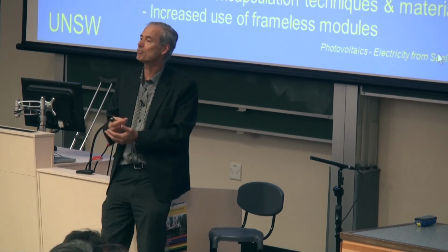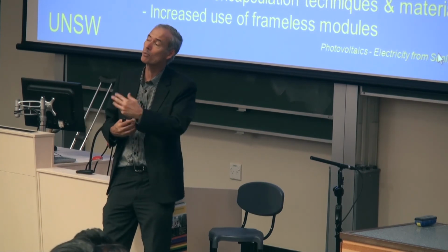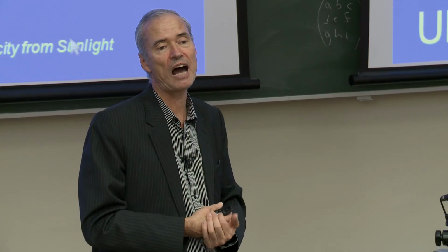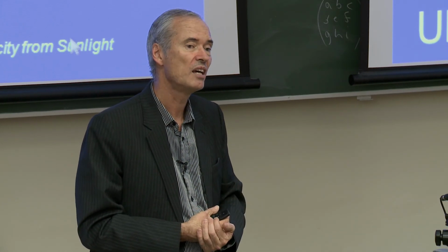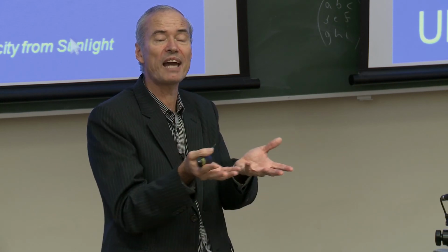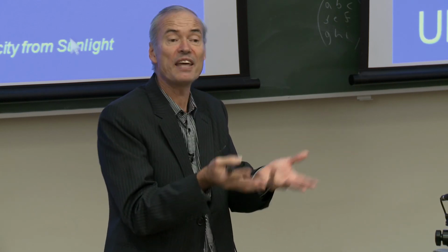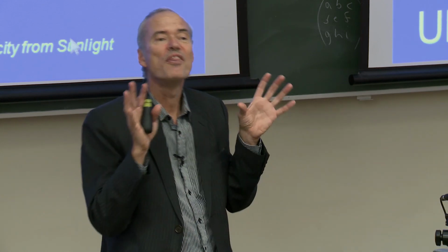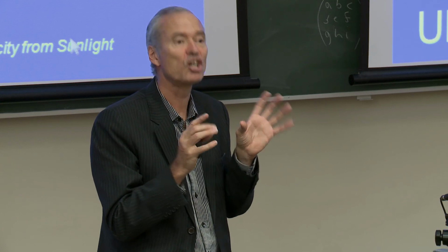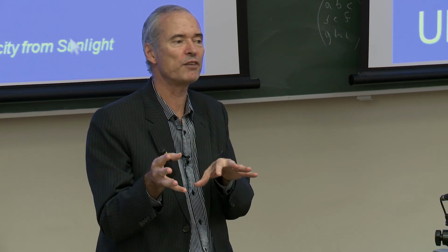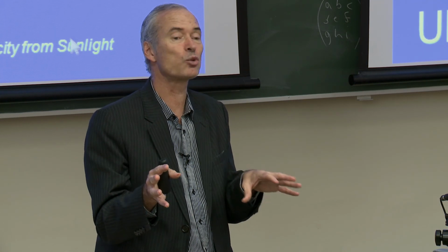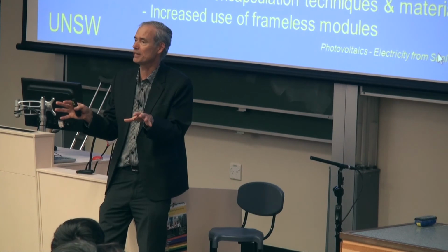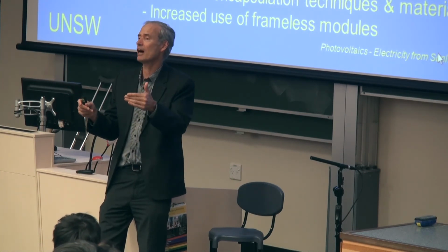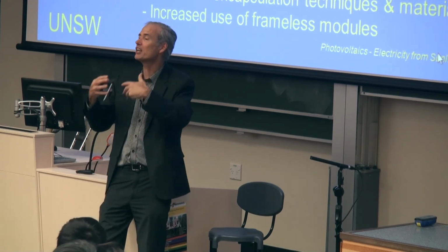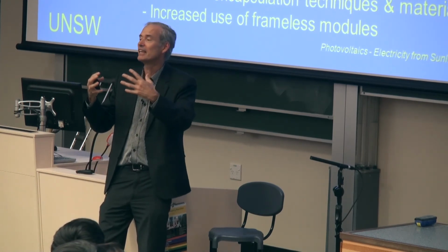And so the typical screen printed solar cell only a few years ago was limited to about 16.5%. It's now at about 18.5%. Some companies are getting up to 19%, and those that are starting to introduce the passivation at the back, they're jumping to over 20%. And that's really important because only 2 years ago, that team of experts that I talked about concluded that silicon solar cells in commercial manufacturing would never get over 20%. And it was going to take until 2020 to even get there to 20%, and that was the limit. And that was their prediction year after year. But as we find more and more of the Chinese and Taiwanese and Asian companies getting involved in that team of experts, the overall feeling is changing.